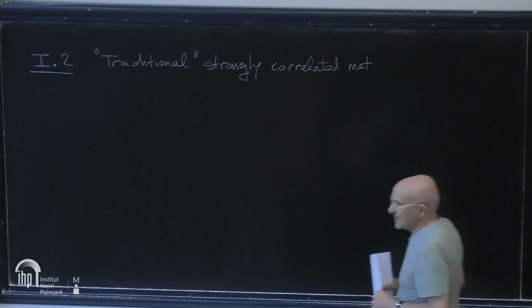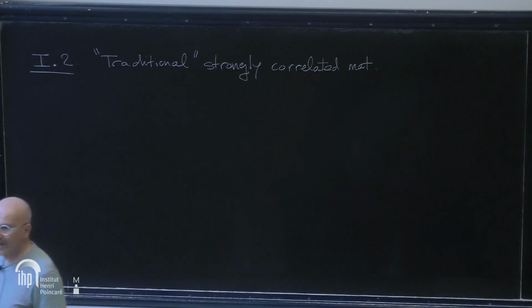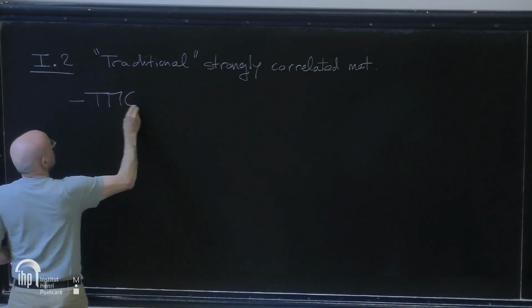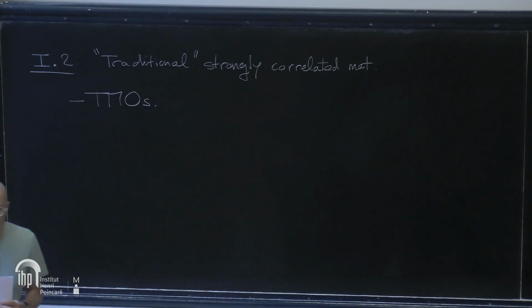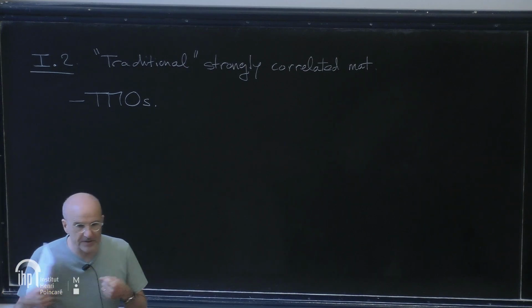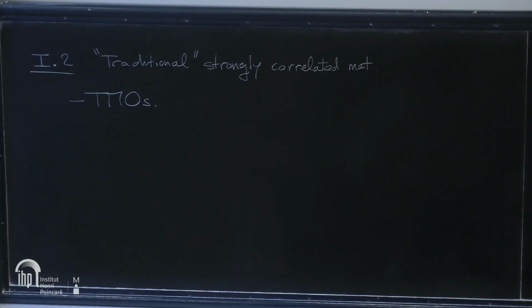Okay, so since then the field has developed enormously. There are thousands of examples of materials which display strong electronic correlations, many of them in the field of transition metal oxides, or TMOs. The reason being that the d orbitals of a transition metal are rather well localized around the nucleus, and so you retrieve this notion of well localized Wannier functions, and hence the overlap between these orbitals from one atomic site to another is relatively weak as compared to the on-site value of the screened Coulomb interaction U. And here I've already said a word which is kind of worrying.